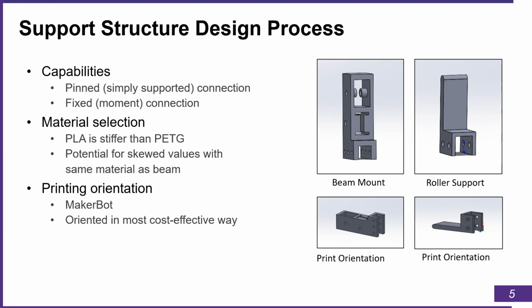And then for the beam mount, we decided on PLA because it is stiffer than PETG, so we wanted it to be stronger. We didn't want any skewed values in the strain. So when we load the beam, we didn't want it to be somehow skewed because it's the same material. So we just wanted something that was stronger than the beam itself, or more stiff rather. And then with the printing orientation, we wanted it to be in the most cost-effective way. So the bottom figures on the right show how it's oriented on the printer. Obviously, if we had printed those vertically, we would have had way more support, and it would have ended up being a lot more filament to use. So we just kept that in mind when we were printing.